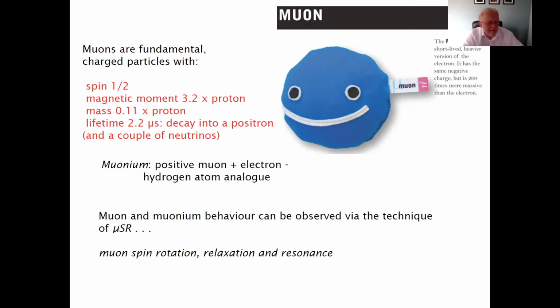And the way that that muon decays is dependent entirely on its local environment. And so for understanding how those positrons are produced from that muon decay, you can understand the local environment within your material, and so you can study how the local environment changes depending upon what you're doing to it, whether you change the composition or you're putting an electric field on it or what have you. So you have another non-destructive probe for investigating materials, and this is becoming particularly important for battery type materials.